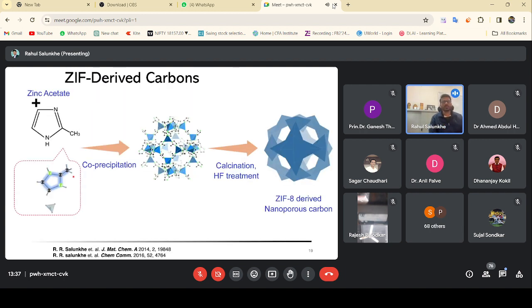So let's first start with the basic MOF-derived carbon materials. Typically zinc acetate and 2-methylimidazole precursors were used, and by co-precipitation we get the metal organic framework ZIF-derived carbons. This is called ZIF-8 because it contains zinc and 2-methylimidazole. There are different names available: ZIF-8, ZIF-67, ZIF-62, ZIF-61. Many series of materials exist depending upon the linker and the metal, and there are various names available in the literature.